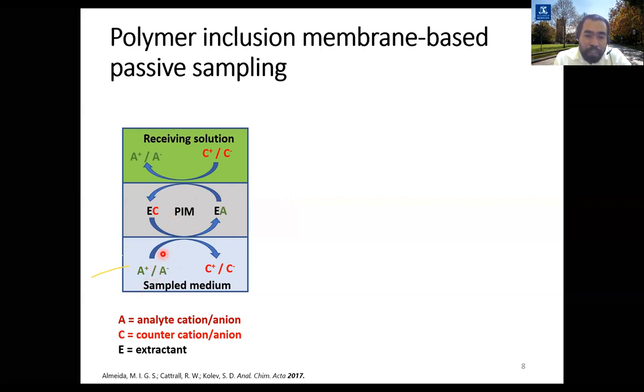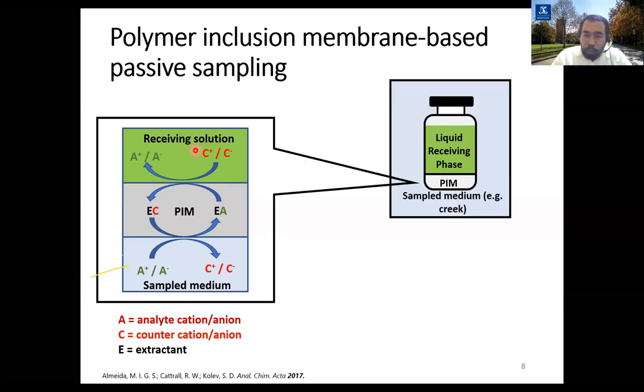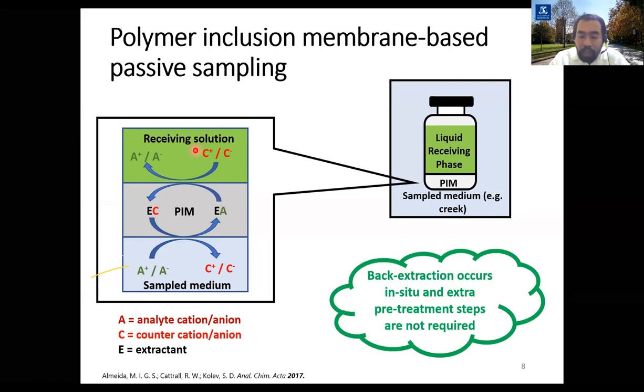What happens is the analyte will first bind to the extractant present in the polymer inclusion membrane. The complex will then diffuse to the other side of the membrane where the back extraction occurs with the counter anion or cation, depending on our target analytes. This property is again utilized in passive sampling devices because we can apply this type of membrane as the semi-permeable membrane barrier, which separates the liquid receiving phase from the sampled medium. Because the back extraction occurs in situ, minimal or no pretreatment steps are required upon the collection of our passive sampling device. Why? Because the liquid receiving phase can be sent directly for measurement.